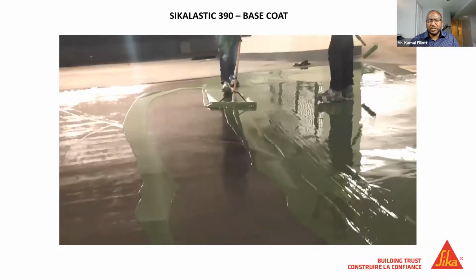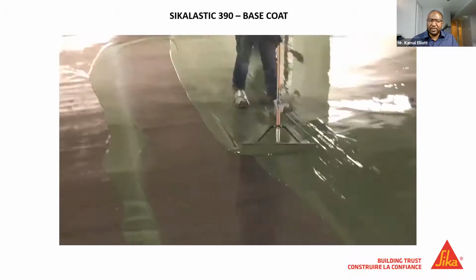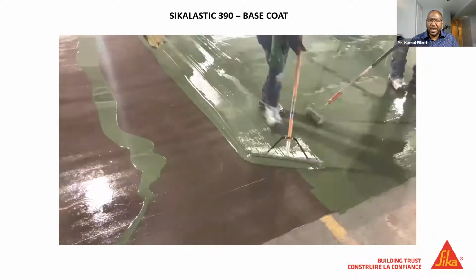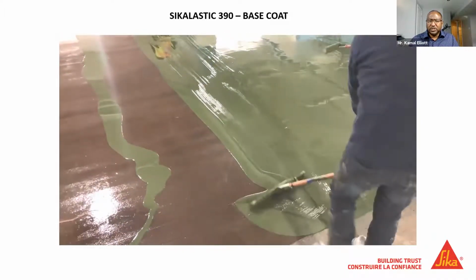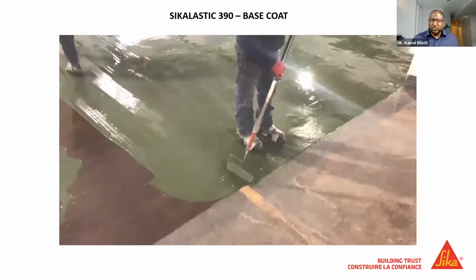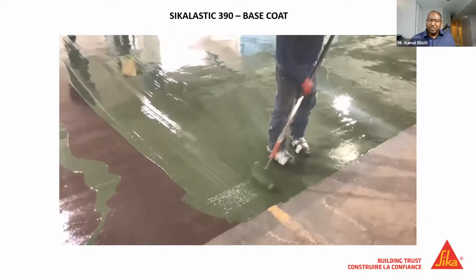And here you see it quickly. This is being installed with a V-notch squeegee to make sure they get the adequate thickness, and then it's also being back rolled. What most contractors will do is calculate by volume for a specific area. The math is straightforward: how much material you need to achieve 25 or 30 mils, and they'll make sure the material goes into that specific area. Often they'll grid out the area and make sure that each unit goes into that area specifically. It's also easy to monitor with wet film thickness gauges to ensure that you're not light or heavy in certain areas. You can do quality assurance on the job to make sure that the membrane is going in uniform.